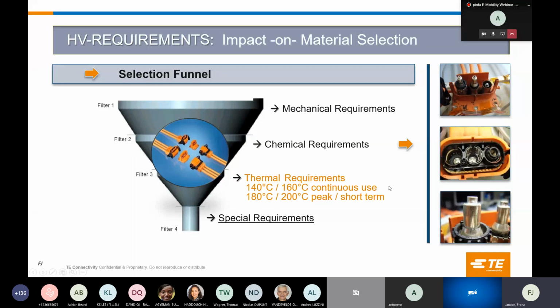What I would like to focus on in this slide is the color orange in our parts. We have here the contact for high voltage requirements. We need to pass thermal test sequences up to 180 degrees C, up to 200 degrees C, and if you select the wrong material, we get more thermal stress on this finger protection. The material was before black or even orange, and then we get a carbonization.